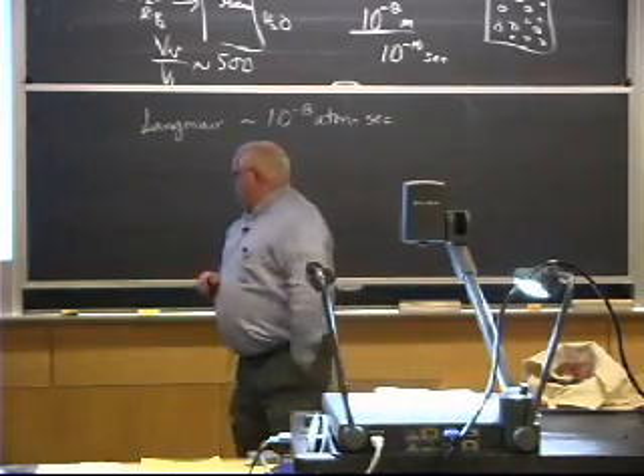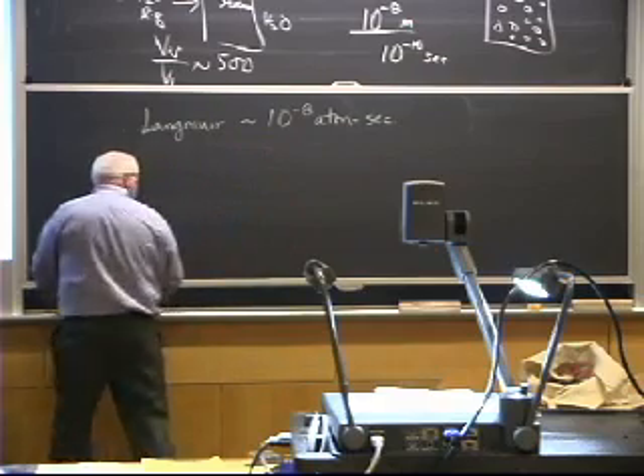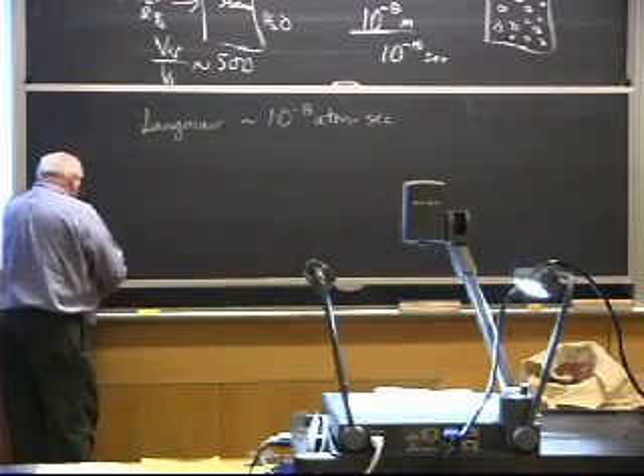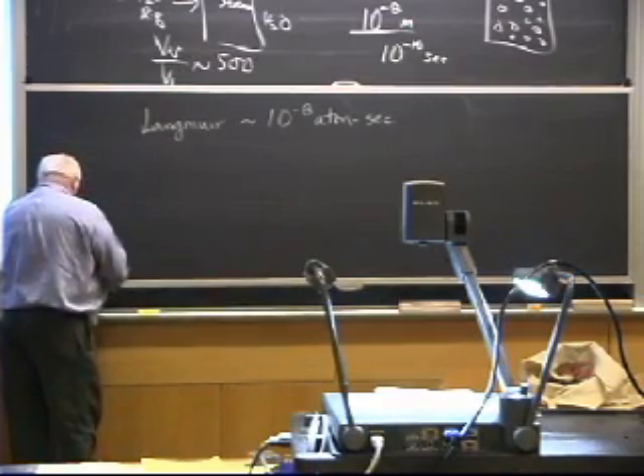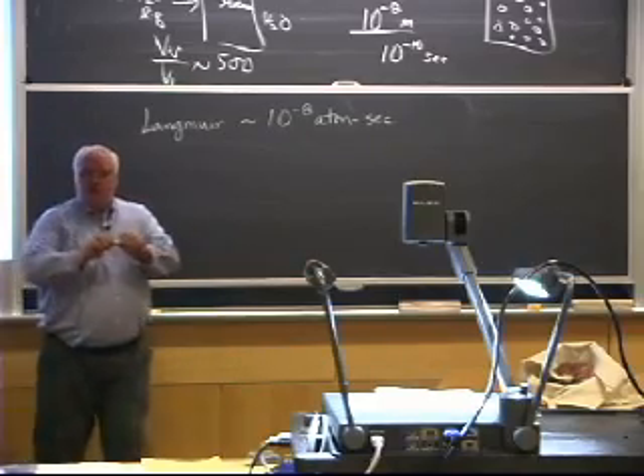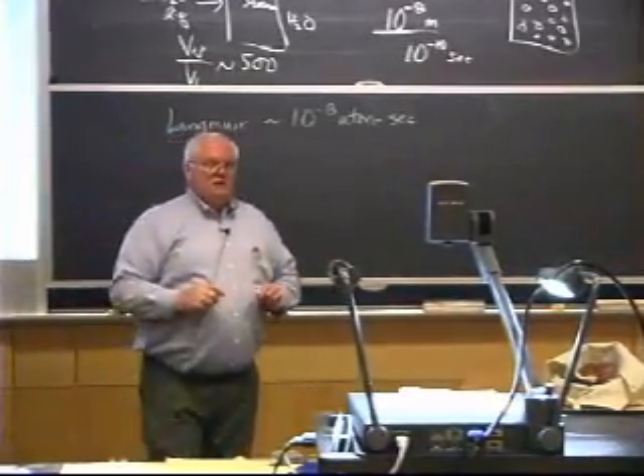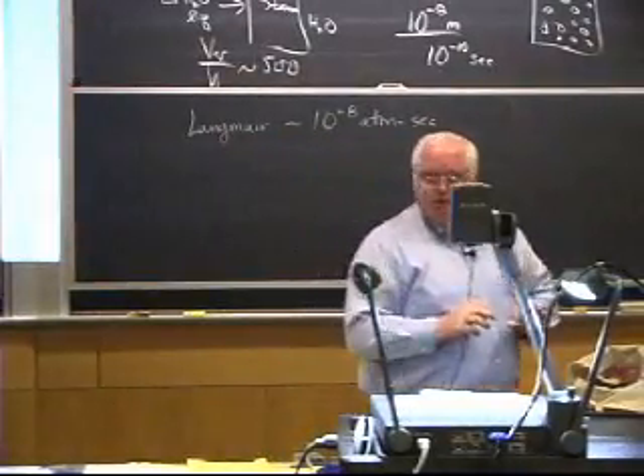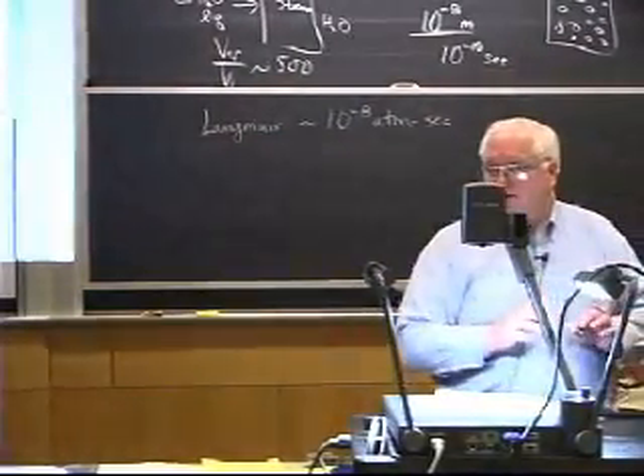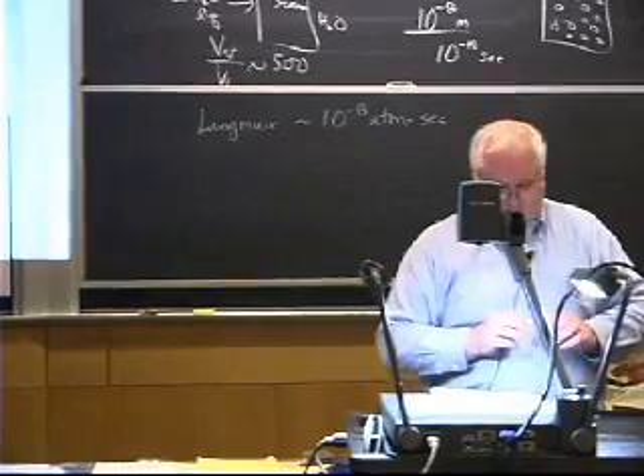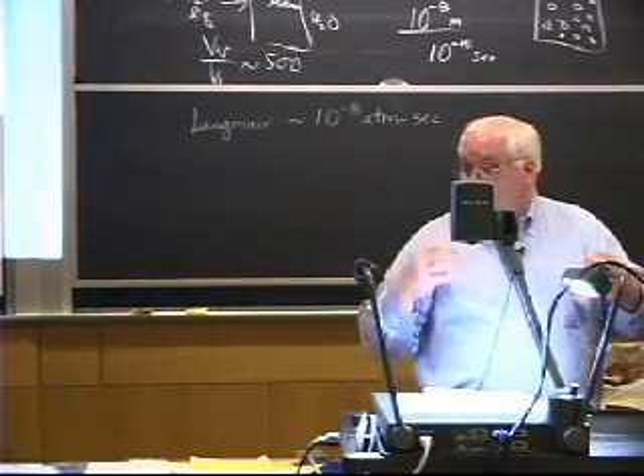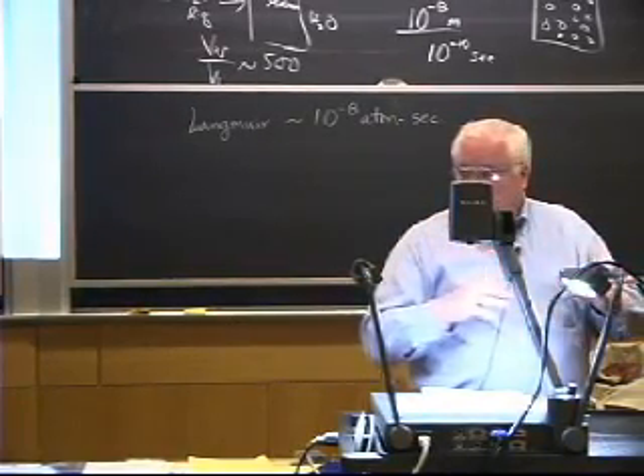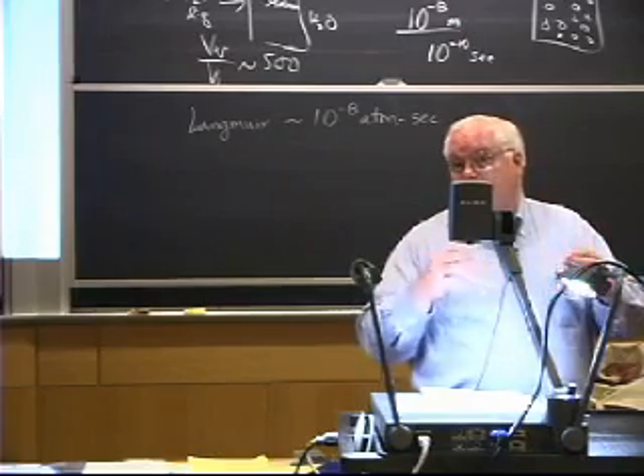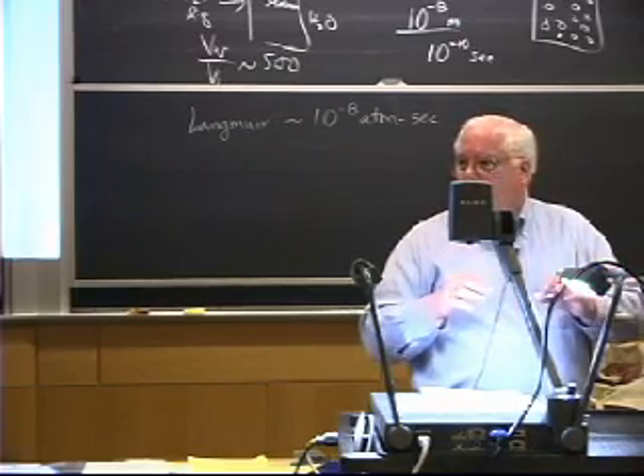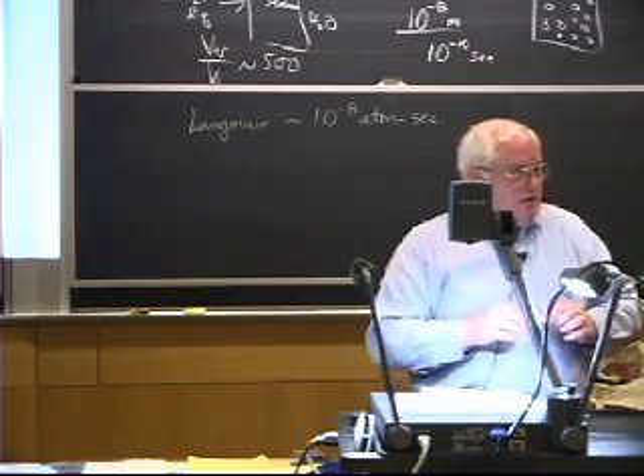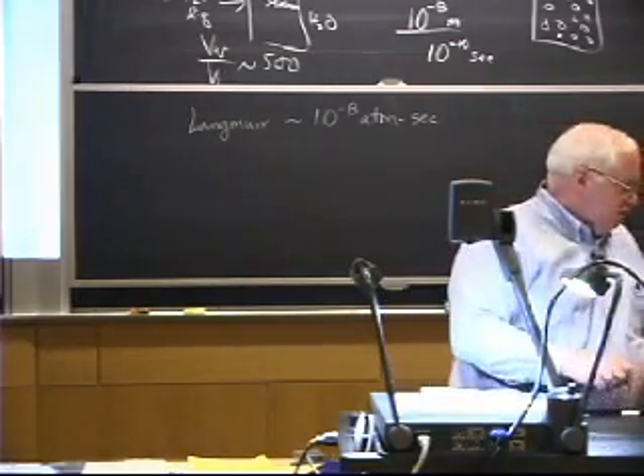So if I took a piece of chalk and I wanted to break it and then re-weld it, I could do that, but I've got to put it back together very quickly, within 10 to the minus 8 seconds or less at atmospheric pressure. If I take a piece of gold and do it in ultra-high vacuum, at 10 to the minus 12 atmospheres or so, I might have a couple of minutes to wait and put it back together. And that's the type of experiment that people did.